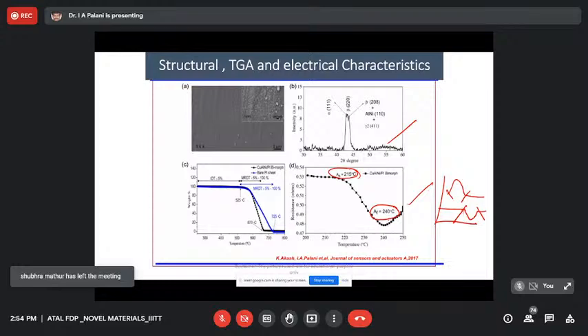Like I have mentioned earlier, for nickel titanium we go for 80 to 130 degrees Celsius, and in the case of copper-based shape memory alloy, we go for 250 to 300 degrees Celsius. So that window is taken care of using this DSC analysis. And this is a TG analysis which we have done. It's a thermogravimetric analysis which we have done to see how the system behaves.